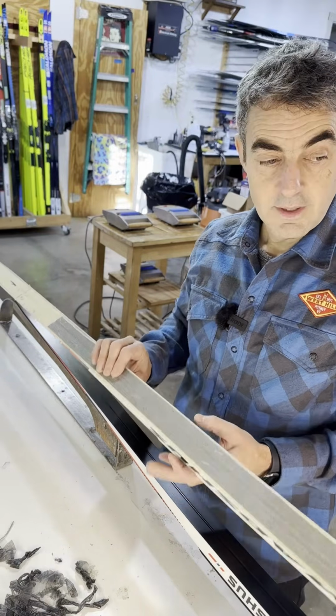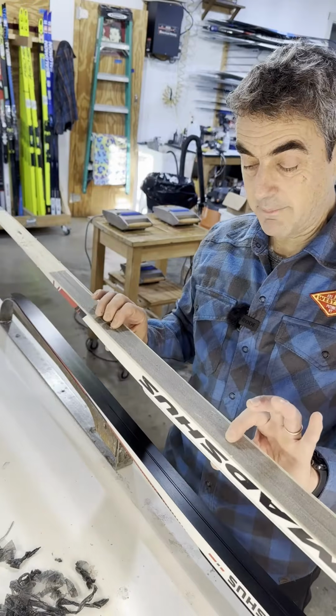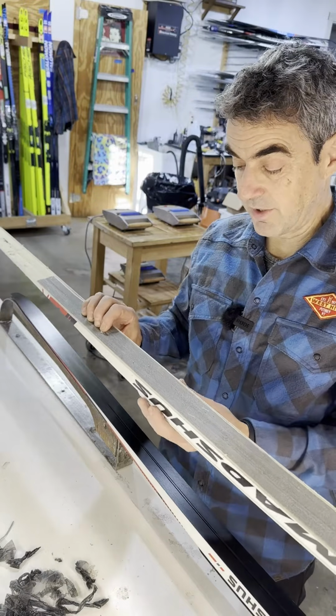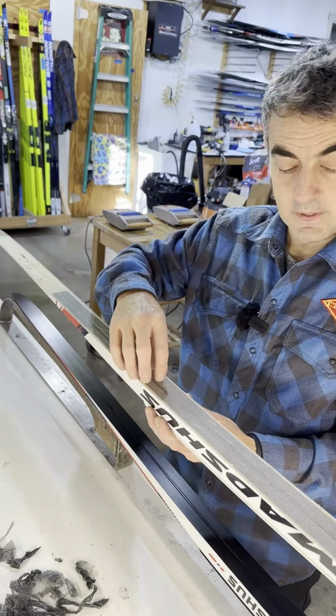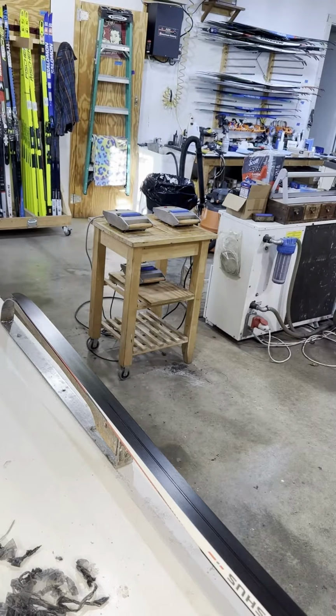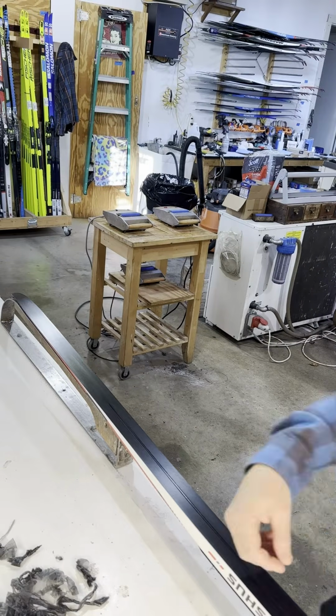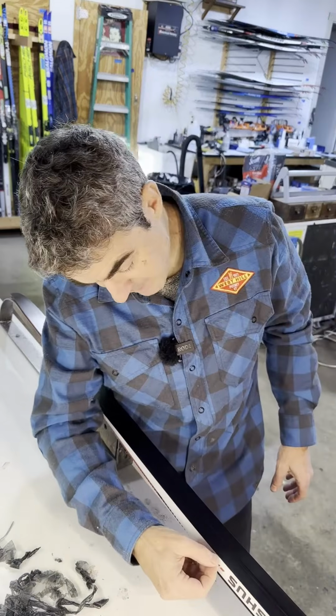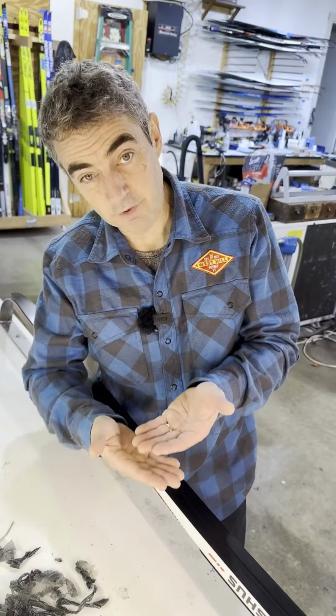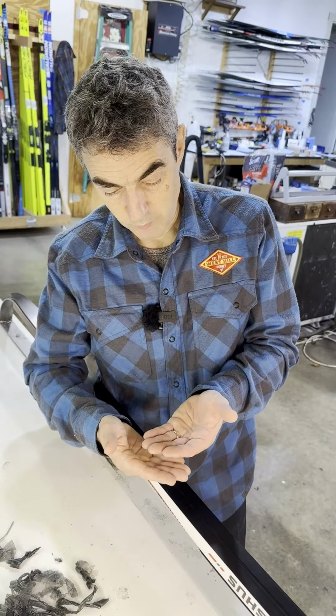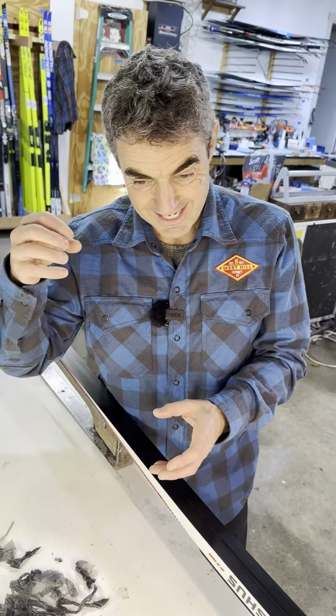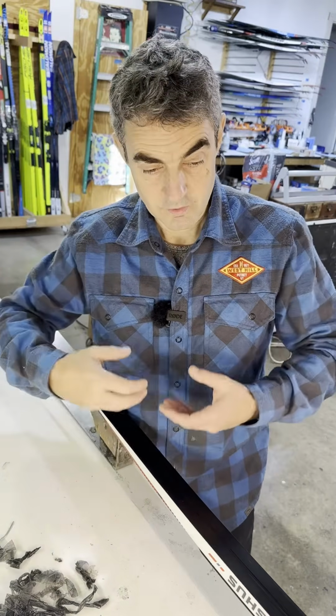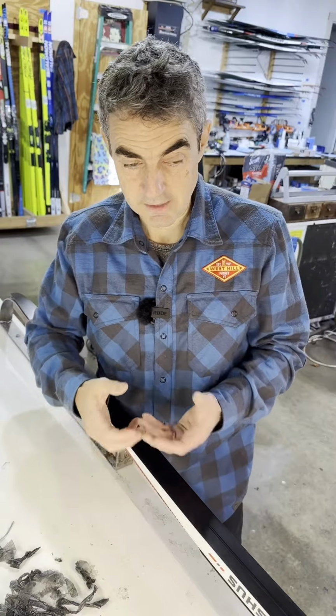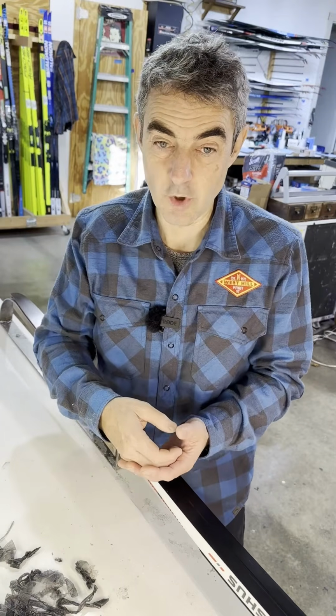As a rule of thumb, I can safely say that we want to keep heat above about 100 Celsius out of the core of the ski. So what that means is that we're trying to work on the millimeter to 0.8 of a millimeter of thickness of base material that we have. And we want to get the heat in to the depth required to allow the wax to penetrate into those amorphous materials, but we don't want to go beyond that.